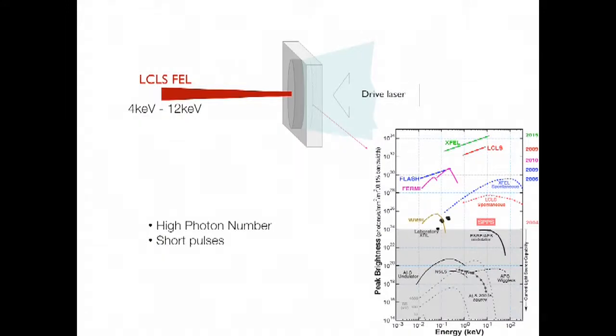So at LCLS, we have this really bright X-ray source, and it's extremely short. So it beats any hydrodynamic expansion, even many of the very fast processes that happen in these materials. So you can create the matter. Generally, we use drive lasers, very strong lasers, and then probe it with LCLS before the changes happen and before the sample has exploded, expanded, and become more dilute.